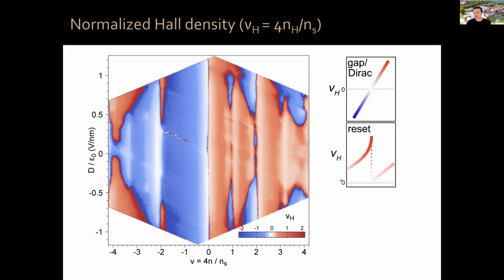Other regions are characterized by what we call a reset in the normalized Hall density. Your Hall density grows and then exhibits a drop close to zero, but without changing sign, and then it continues to grow. This can happen for red, so light red, dark red, light red, dark red, or with blue. Perhaps this is most pronounced here. You can see that this goes from light blue, dark blue, then white, then lighter blue, darker blue. There's a reset that happens there.